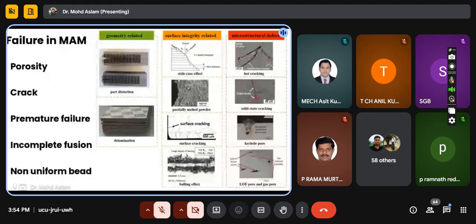Here are some of the figures I have mentioned, geometry related defects, like part distortion and part delamination. After that, stair-case effects are also shown, which are surface integrity related, and here partially melted powder. We can easily see partially melted powder produces premature failure, and surface cracking is also there, and the balling effect